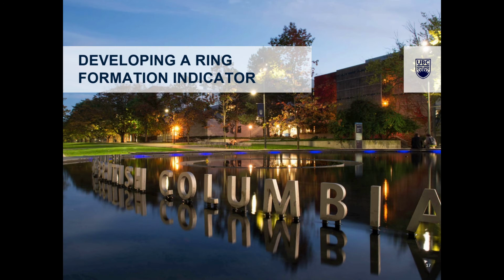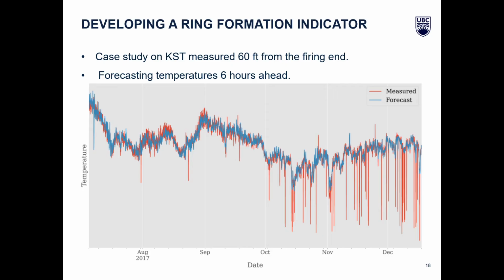Now that we have visualized the data and prepared it for further analysis, I'll present a brief case study that demonstrates our ongoing work to develop a ring indicator. This figure shows the shell temperature data from the largest experimental trial at the 60-foot position. The red line is the measured data, and it shows some large temperature drops that are not typically characteristic of shell temperature measurements. The blue line is a time series forecast from an autoregressive statistical model.